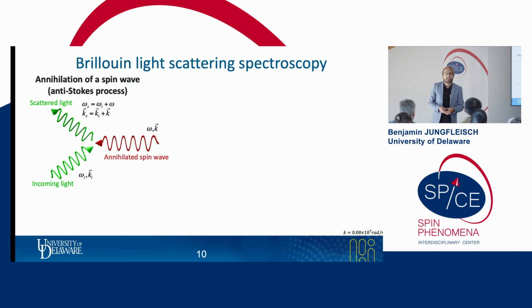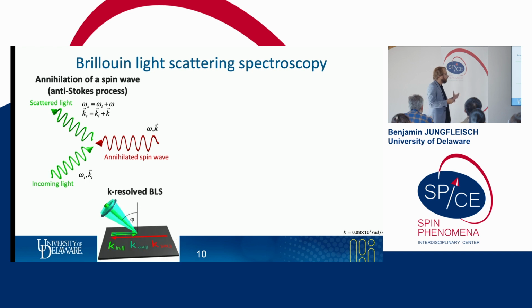Now let's switch to the dynamic measurements. We are going to use Brillouin light scattering spectroscopy, which is an inelastic scattering technique. So we can either create or annihilate a magnon. This process is energy and momentum conserving. So we can analyze the inelastically scattered light that carries information about the probe magnons. So we analyze this tiny frequency shift. And if we use a macro BLS system and vary the angle of incidence with respect to the film plane, we can also reconstruct information about the wave vector. We do this in a Damon-Eshbach geometry where the magnetization and the wave vector are perpendicular to each other.